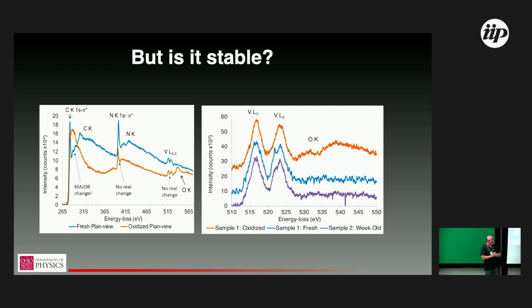The electron energy loss provides insight there as well. And so this is stability measured, or degradation measured, on two different axes. Here, the blue curve represents a sample that's transferred essentially unperturbed from the growth chamber into the TEM and measured, focusing on this sharp spike on the low energy side, and this peak here associated with the carbon. And then the orange curve is what happens when you leak some oxygen into the chamber before measuring. And you can see dramatic changes in the carbon lines, but not much change in the nitrogen line.